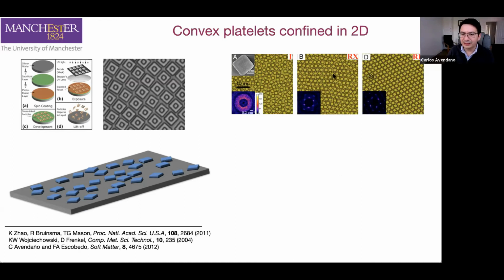And the formation of that hexagonal lattice can be observed also from the scattering experiments, where you can see the formation of these hexagonal Bragg peaks that basically indicate the formation of that hexagonal phase. And at higher densities, so at the bottom of that sample, what you observe is the formation of a rhombic phase. These two phases do not make any sense if you just think about squares.